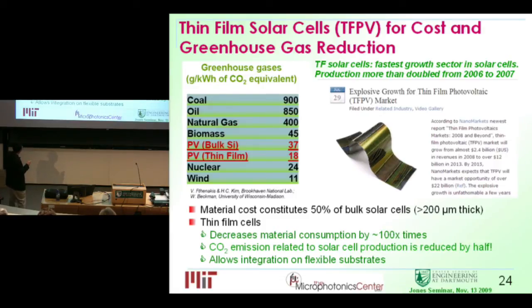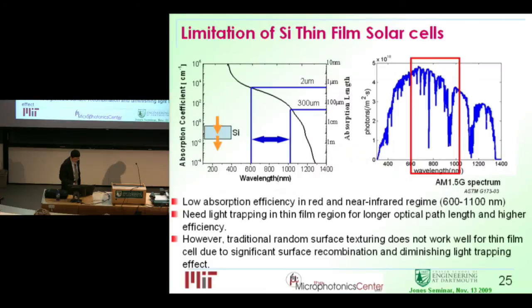And because it's low temperature processing, you can even think about depositing this on a flexible substrate and pasting it everywhere. In terms of CO2 emission, you can see bulk silicon is already pretty competitive. If you reduce to thin film silicon, that will cut this by at least half, because you need less material. And all these advantages drive the boom of thin film solar cells. Thin film solar cells are the fastest growing of all solar devices, and production more than doubled from 2006 to 2007. It's still keeping strong growth in the solar industry. So this is the technology to go.